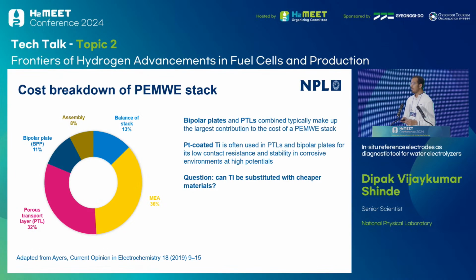So in a proton exchange membrane electrolyzer stack, the porous transport layer mentioned there and the bipolar plate make up the largest contribution to the cost of the stack, and that's because platinum coated titanium is used as a material for bipolar plates and current collectors because of its stability in corrosive environments. So it's assumed that on the anode side, because of high potentials and acidic conditions, you need to have a stable material or a noble metal coating for it to be stable under those conditions.